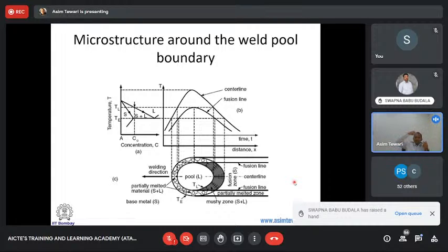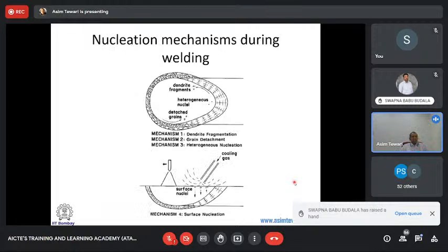This is the temperature range in which you will have both solid and liquid. So once you are forming a single bead in additive manufacturing and going forward, within the melt pool you have large variations of temperature, and those lead to large variations of phases. You have solid outside, complete liquid inside, and in between a mushy zone. Now, having said that, just a mushy zone is not sufficient. Why? Because you also have a very large fluid flow occurring in these liquid melt pools. The previous modeling which I showed you was a macro modeling where we were ignoring this. But we also do modeling in which we look at the individual melt pool model.